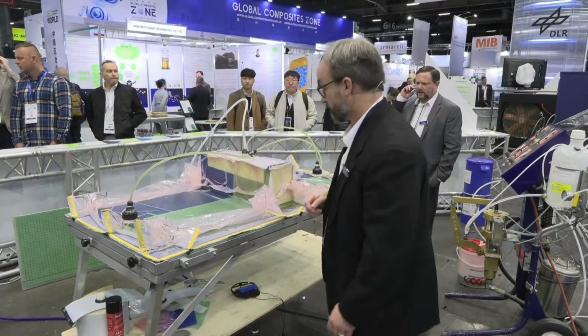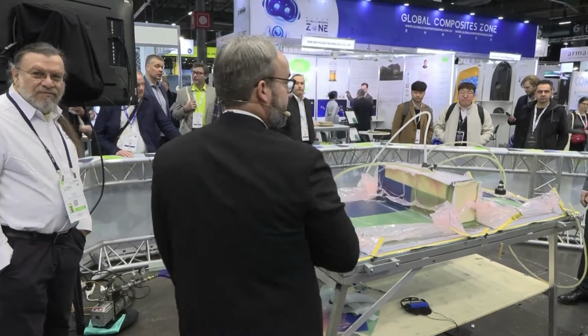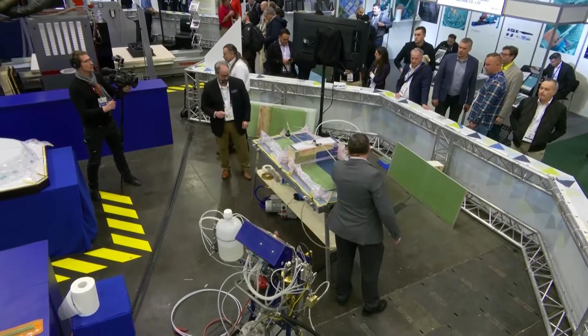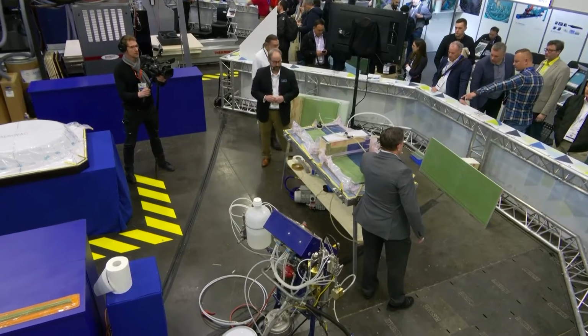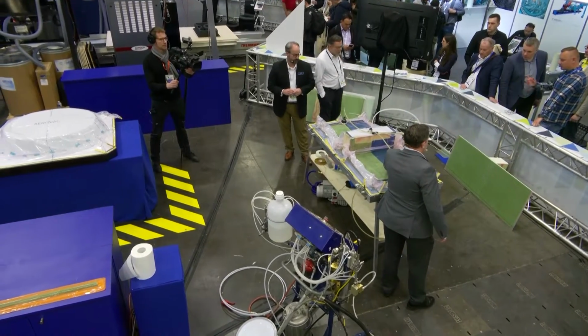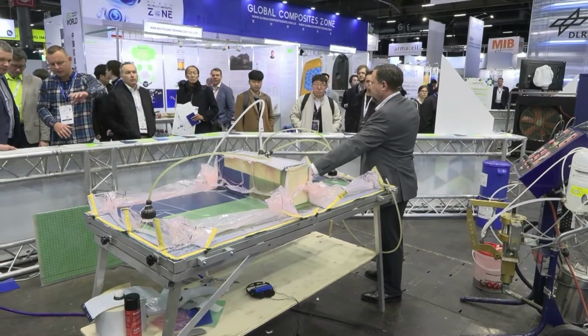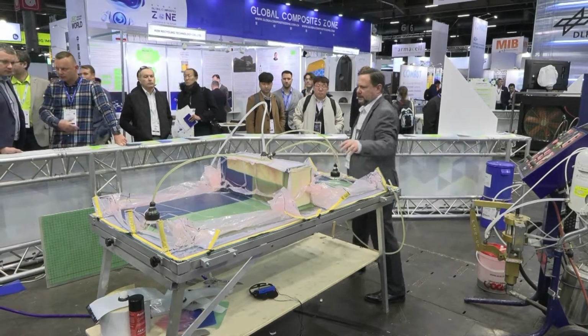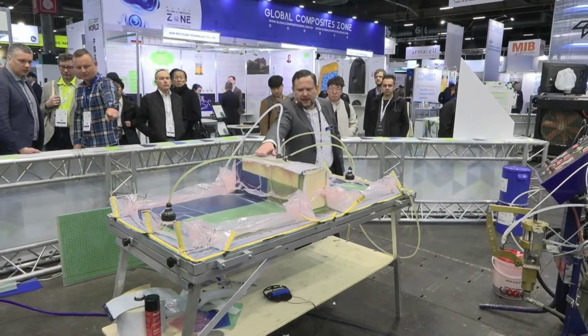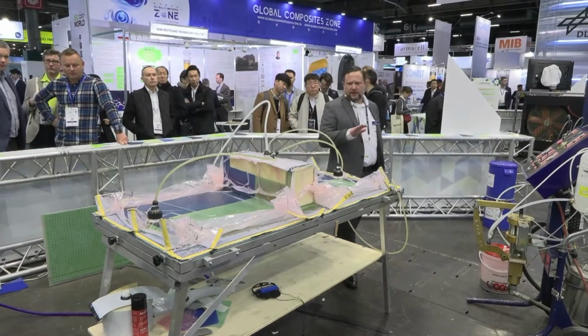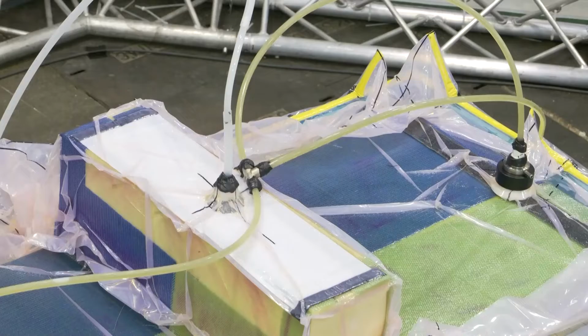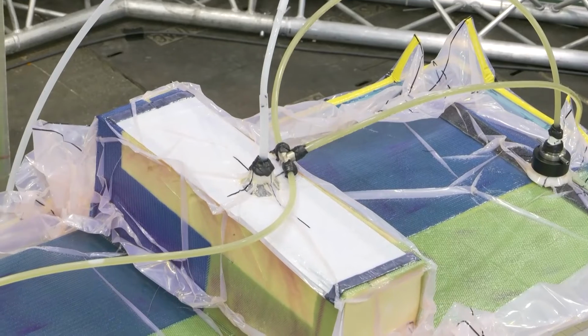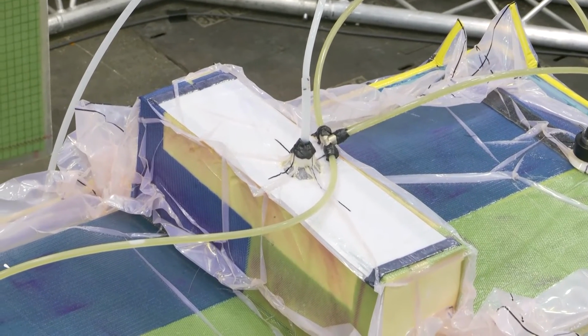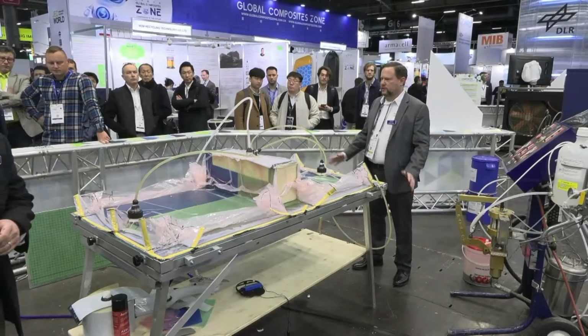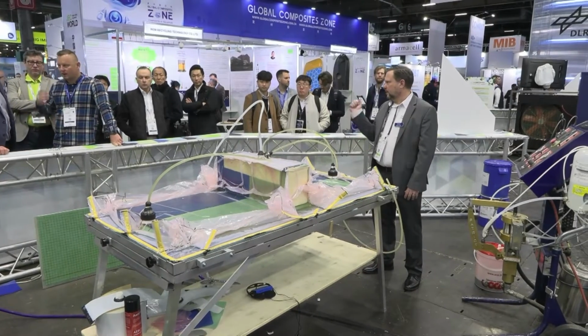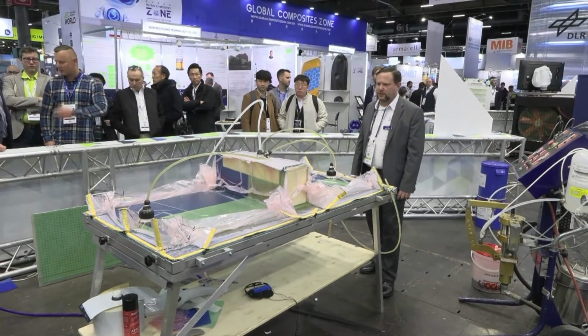And just to reiterate a couple of the impactful process materials here, the InfuPly tube, it's very conformable. It'll go over contoured parts. It's a 2-in-1. It's a self-releasing flow media, so it's very easy and convenient to use. And again, our VMS3 that we're using for our vacuum line, it has a lot of advantages. You can put it right on the laminate surface with no mark off. You can place it in an area that is difficult for the resin to reach. Maybe it's a thicker area. It's a feature to ensure that you fully wet that out, and then it strips away cleanly and easily at the end of the infusion process.